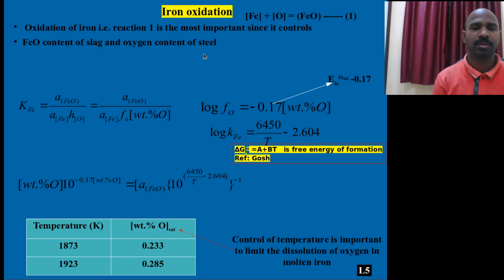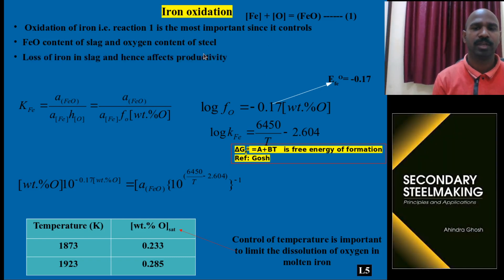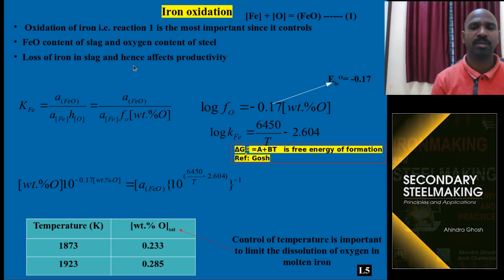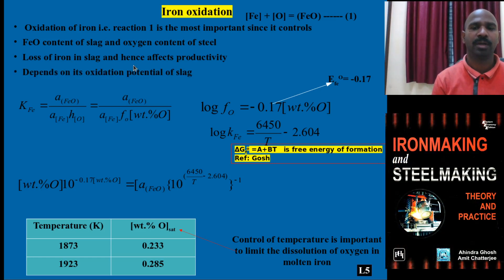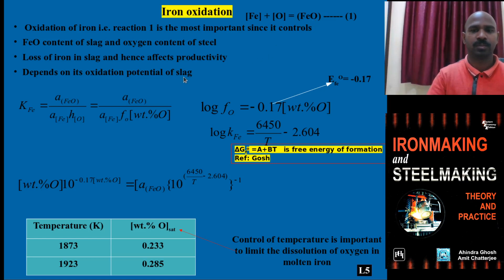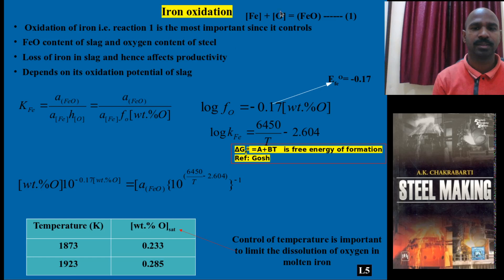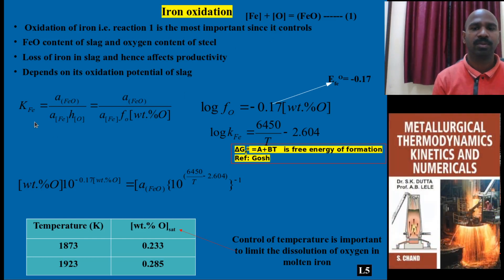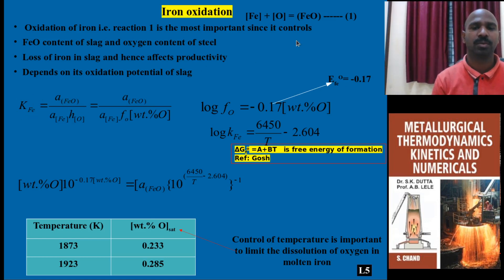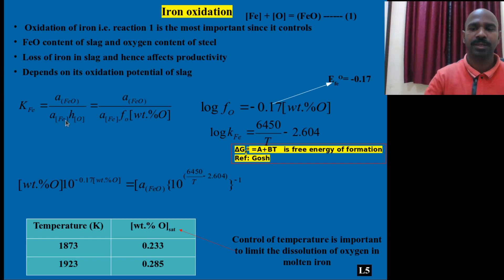Both these things are not favorable — loss of iron is happening. Hence it affects the productivity and the yield of iron is low. How do you control it? It depends upon the oxidation potential of that particular FeO slag. By applying Raoult's Law for these slags and Henry's Law for the molten metal, you can calculate the equilibrium constant with respect to the iron, activity of FeO, and activity of iron and oxygen.